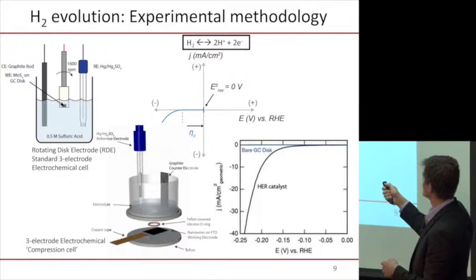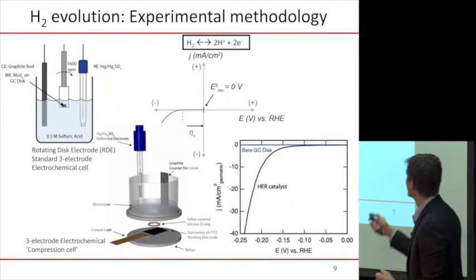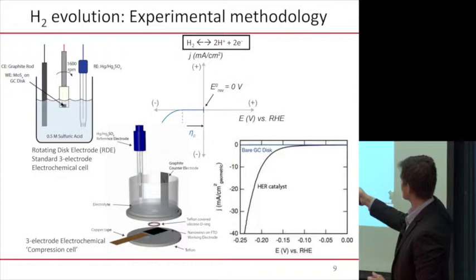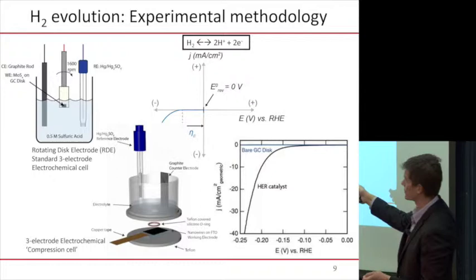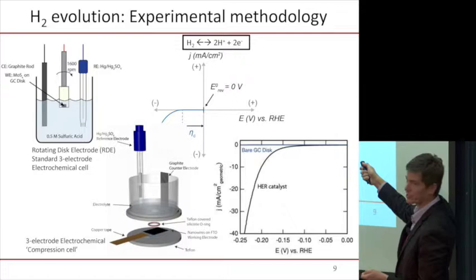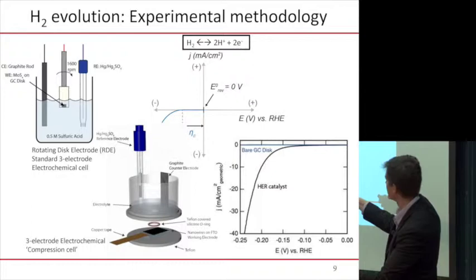And I'm going to be showing you some data, just to be pedagogic for a moment. How we normally look at this type of information is on a current-voltage curve. Zero is a very important value on the x-axis. If your electrode is positively charged with reference to zero, then you actually favor the oxidation of hydrogen to make protons. If you actually want to make hydrogen, then you want to tilt your electrode to the negative side of zero. And the amount of current that you get out is telling you how fast that reaction is running.